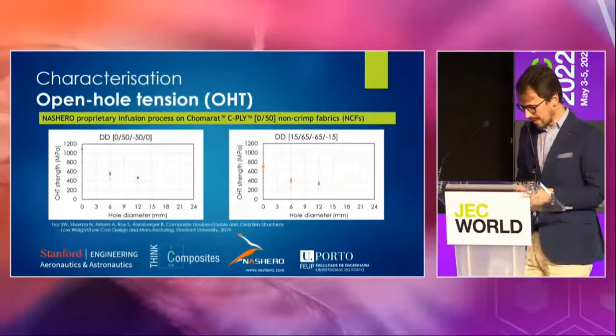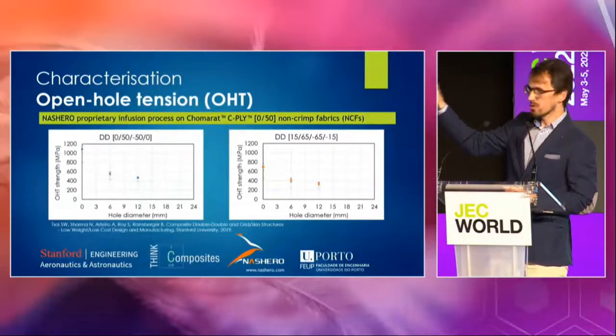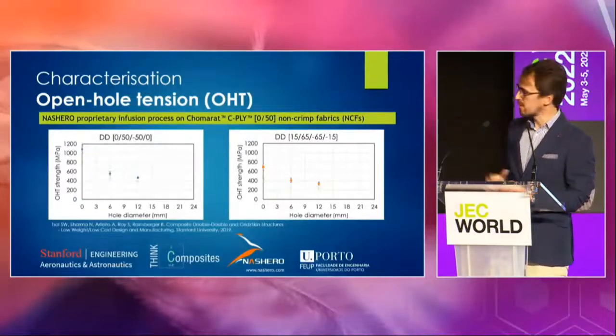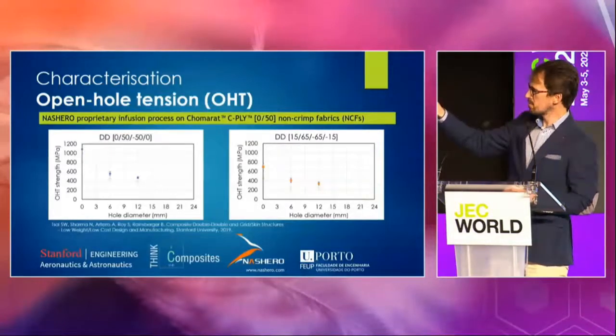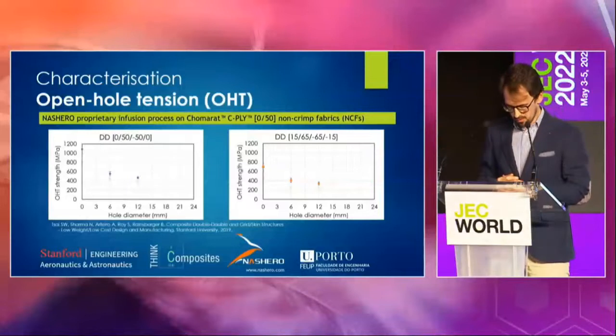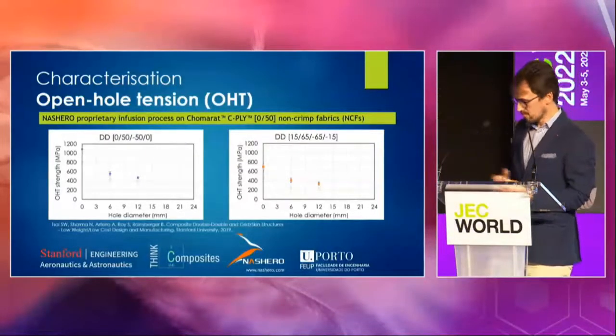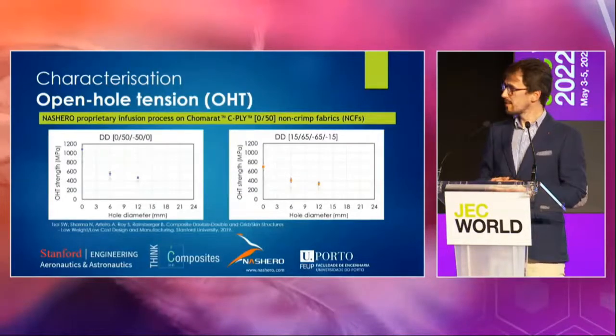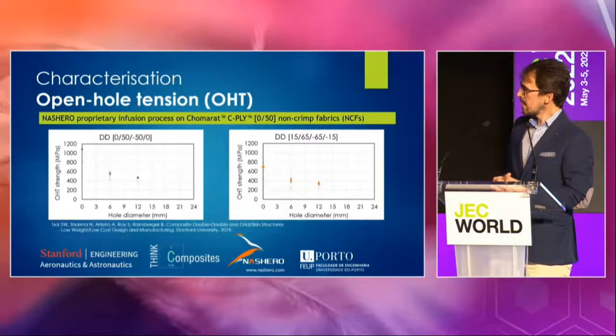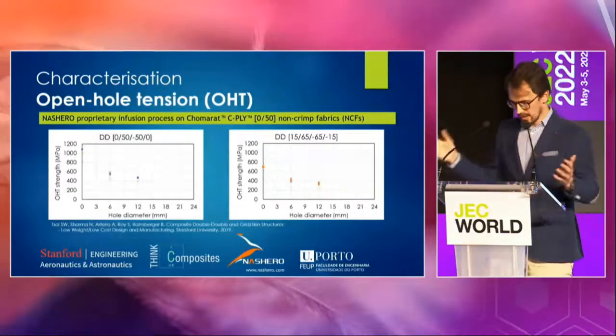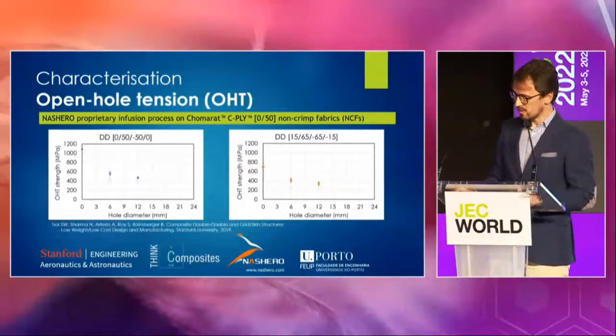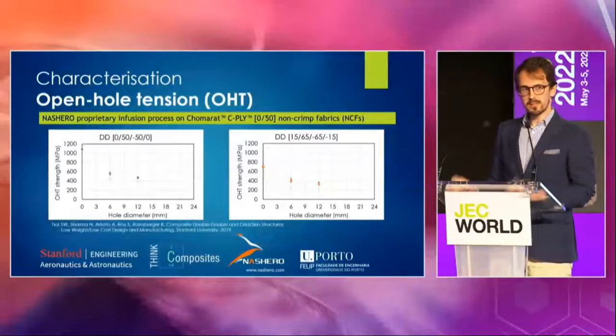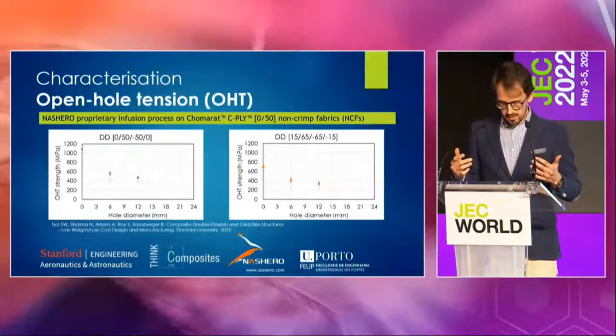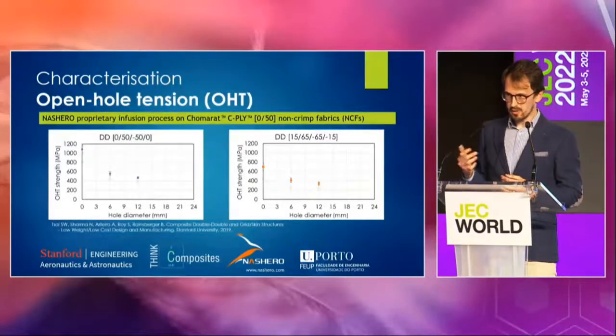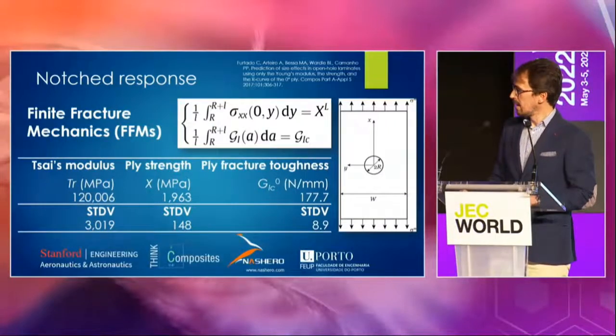So we also tested open-hole laminates, and what you see here on the left, for the hole diameter equal to 0, those are the unnotched strength from the previous slide, and then you see a few tests on two geometries with an open hole, where you see this common notch size effect. You see in full the mean values from those tests, and in the open bullets you can see the B values. So this is not, as I was saying, different from what you do with other materials. Now the question is, what type of flexibility could double-double bring in terms of designing, for example, for notched strength of composite laminates?